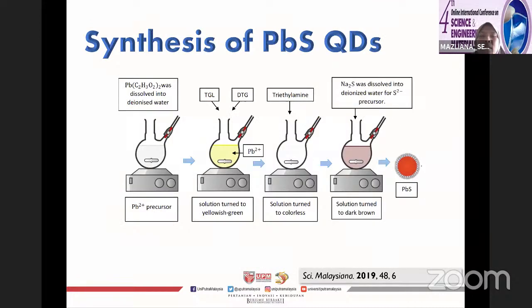So these are the details of the steps for how we synthesize the PbS quantum dots. First, we dissolve the lead acetate in deionized water, and this becomes our lead precursor. Then we add a capping ligand, which in my project is a thiol, where I mix thioglycerol and dithioglycerol. After that, we adjust the pH using triethylamine until we reach pH 11.